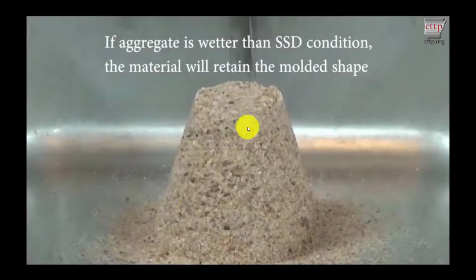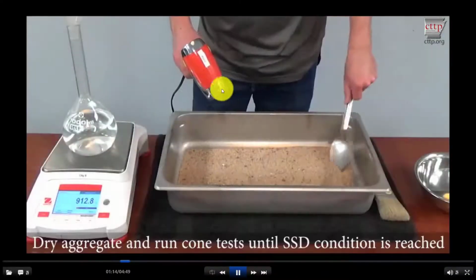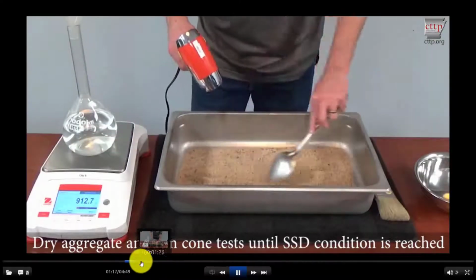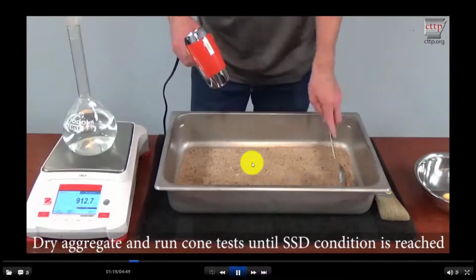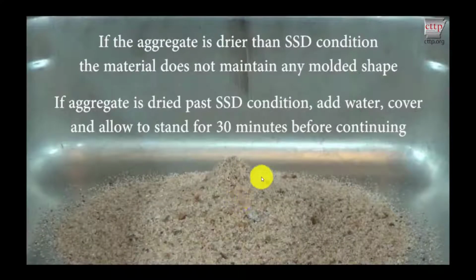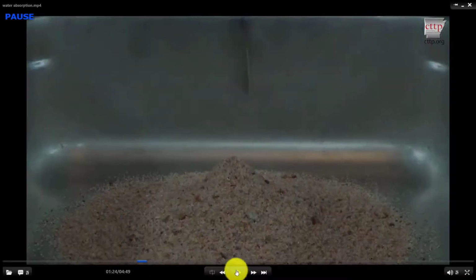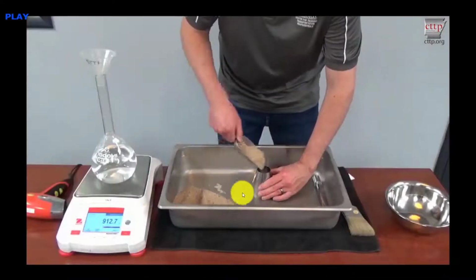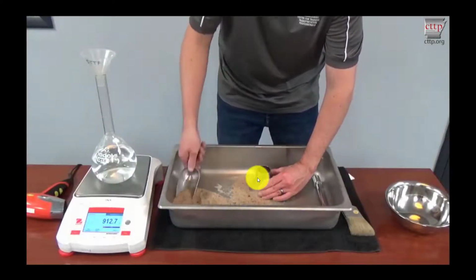I think aggregates are a little wetter than SSD condition. You will again remove the excess amount of water so that the slump retention, the cone retention would not be. Here you have over dried the specimen so that there is no cone formed. So you have to sprinkle a little amount of water and allow it for 30 minutes so that it can absorb the water into the pores. Then try it again for making this mold.